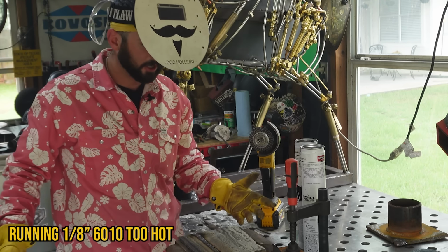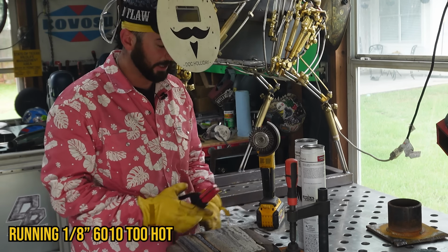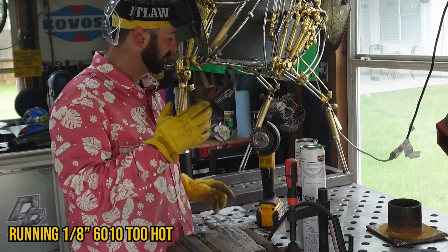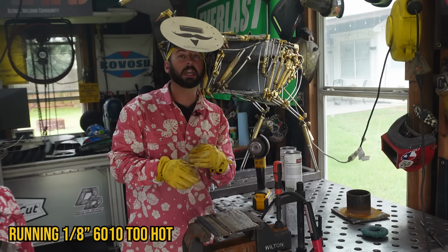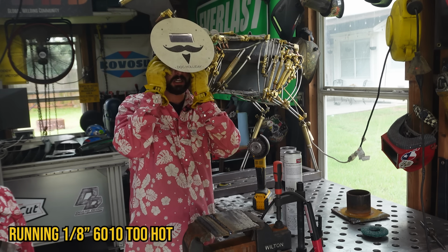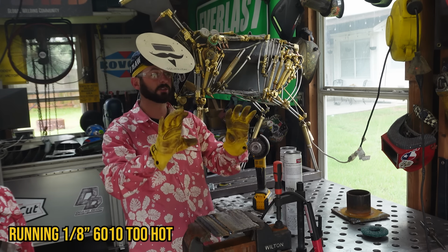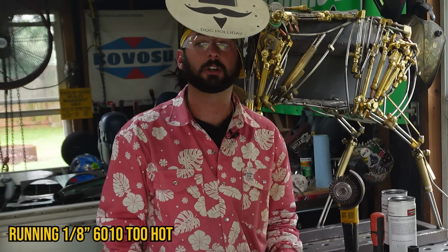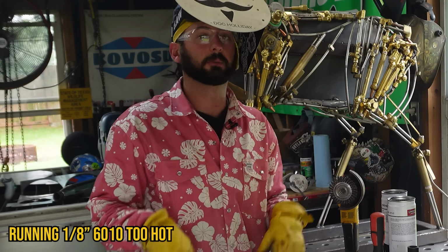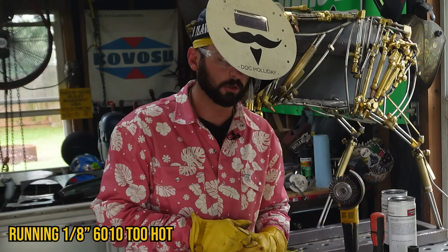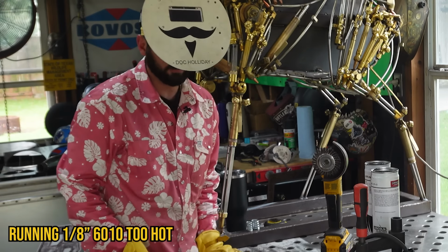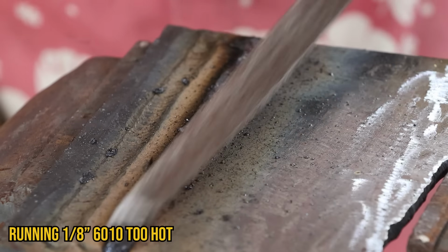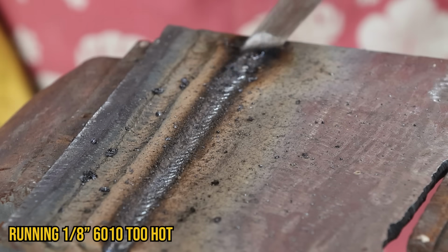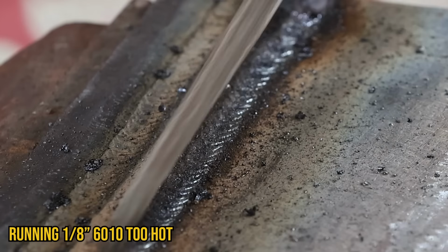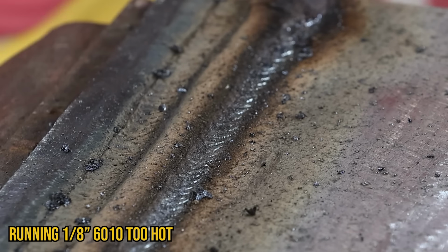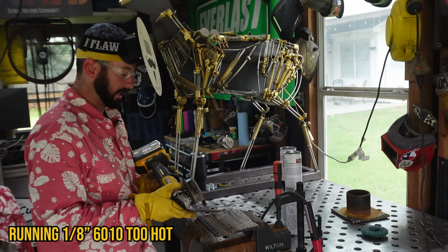Same thing, wider bead, flatter bead, maybe a little bit more spatter. And in the flat position, things just seem to work out for you at a hotter amperage. It's when we go vertical, even horizontal, those things want to start sagging. We're going to have to start turning our amperage down so that that puddle can stick a little bit better. But there's going to be a point where things are going to be too cold, and we'll get into that. Again, you know you've done right when that slag is easy to remove. And again, with it being hot, dude, this thing doesn't look that bad. This is well on the top end of its amperage range recommended before we want to get a bigger rod.